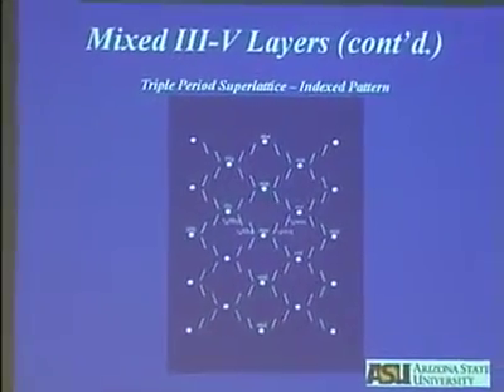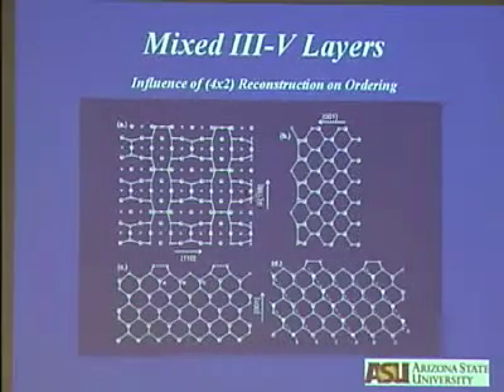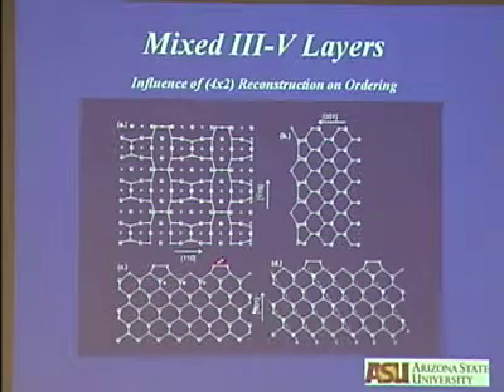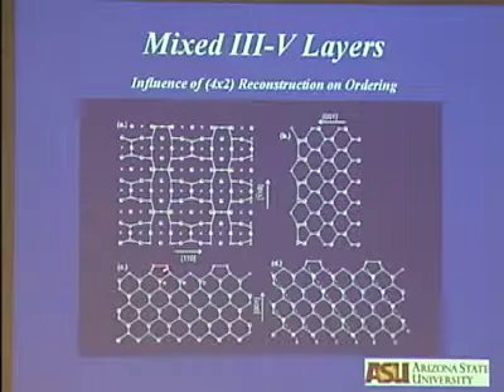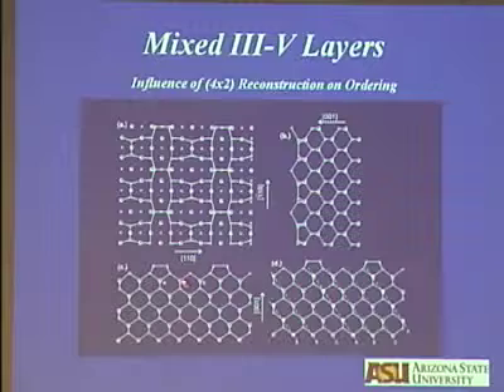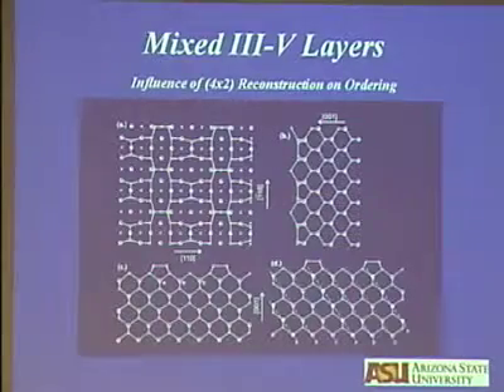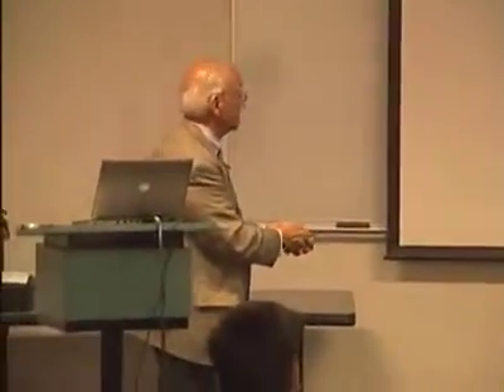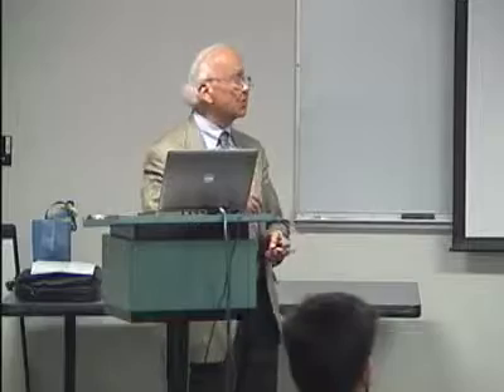Now, how do you explain the evolution of this ordered structure is shown here. When you have a 4x2 reconstruction, this is the structure that you should focus on. You have a reconstruction that produces a compressive stress. This is a tensile stress, compressive stress, and tensile stress. So in the earlier case it was compression, tension, compression, tension. Now you have compression, tension, tension, compression, and that changes the ordered structure. So we can explain why these ordered structures occur, related to the stresses induced by surface reconstruction. 2x4 leads to a double period superlattice, and 4x2 leads to a triple period, but you have to have a size difference in the atomic species of your materials.